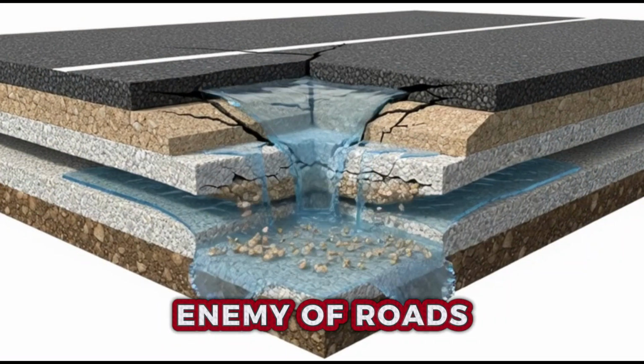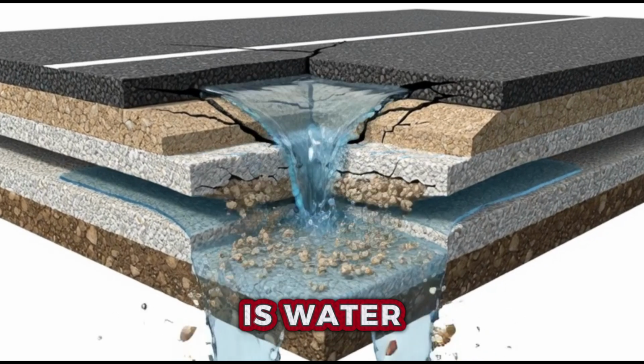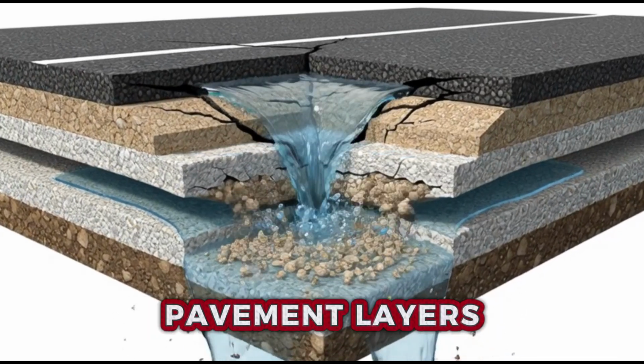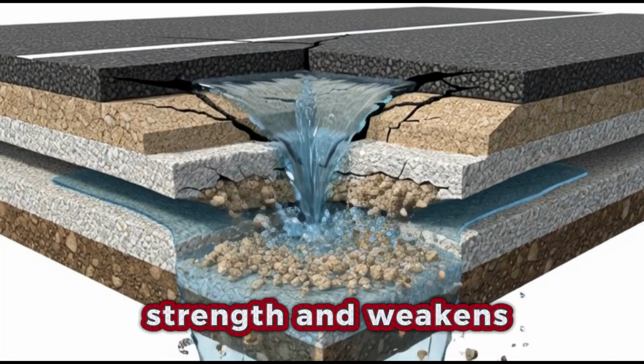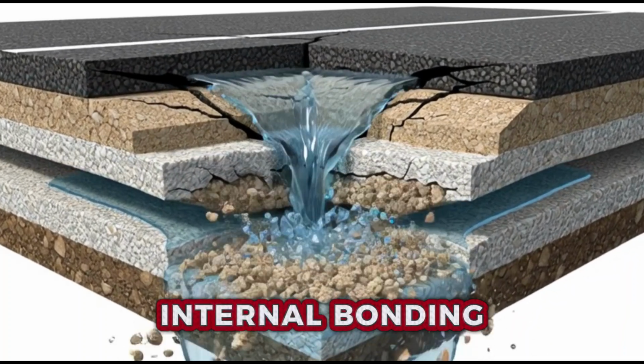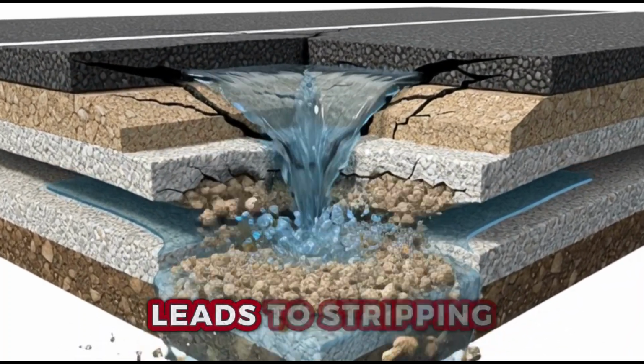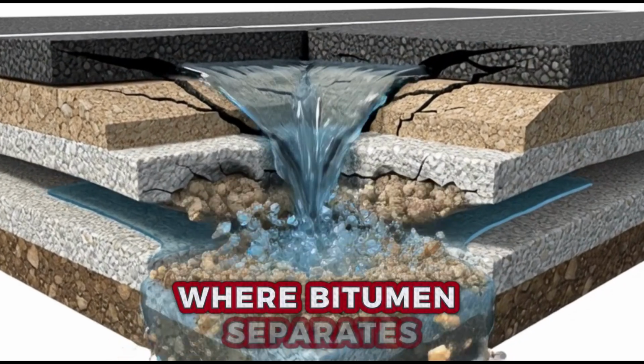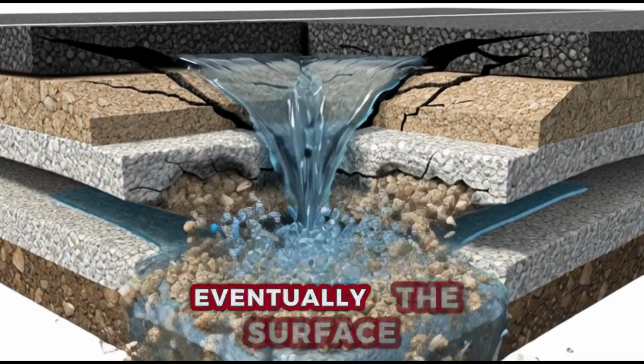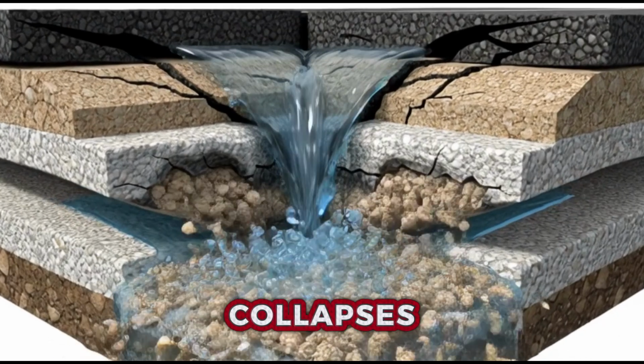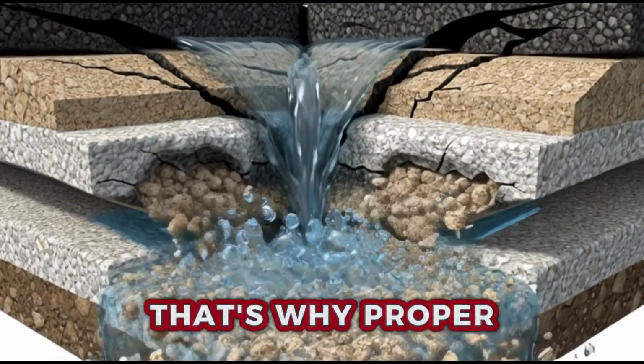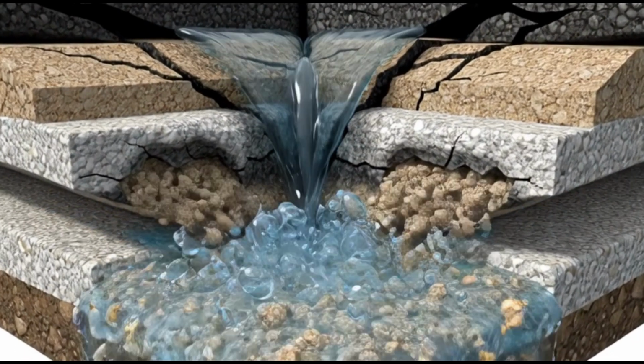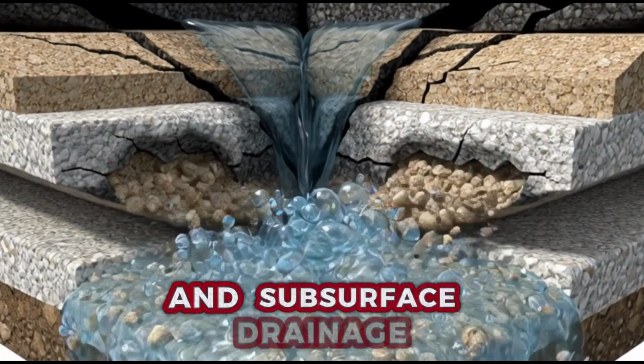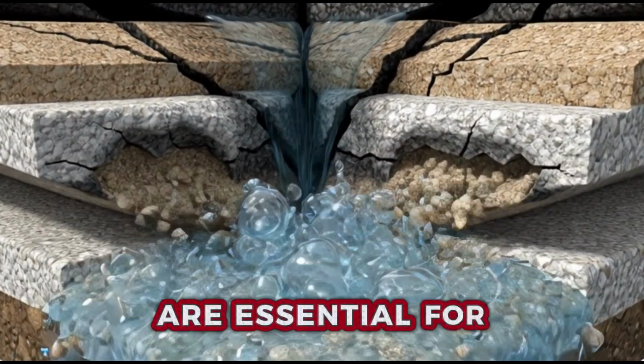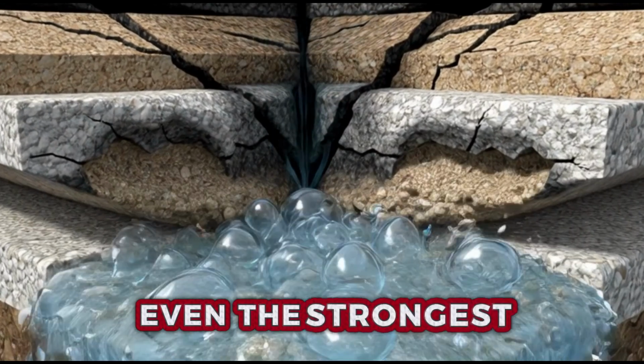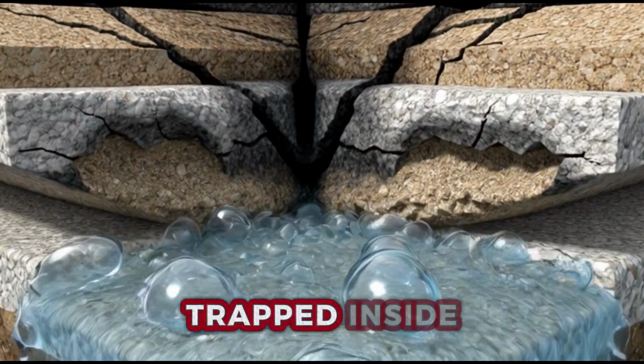But the greatest enemy of roads is water. When water enters pavement layers, it reduces shear strength and weakens internal bonding. Over time, this leads to stripping, where bitumen separates from aggregates. Eventually, the surface collapses. That's why proper drainage design is not optional. Camber, side drains, and subsurface drainage systems are essential for survival. Even the strongest pavement will fail if water is trapped inside.